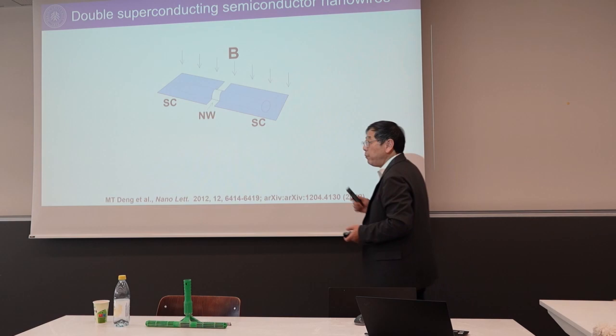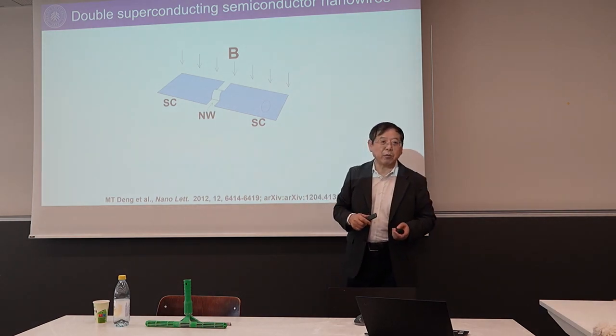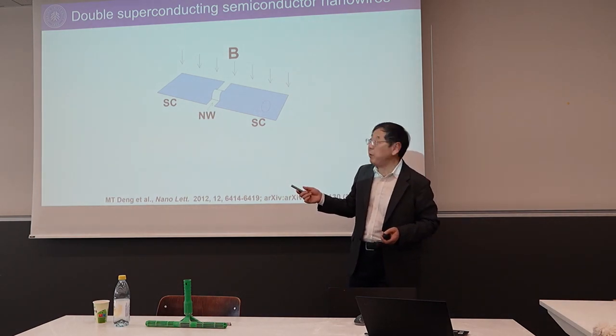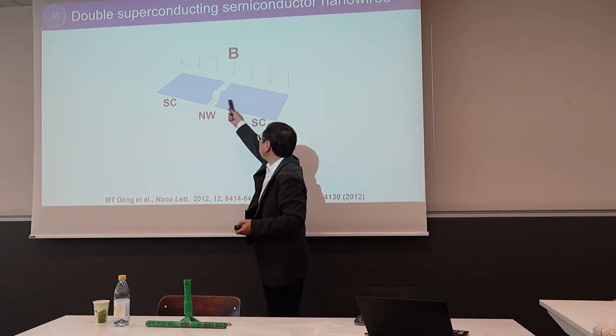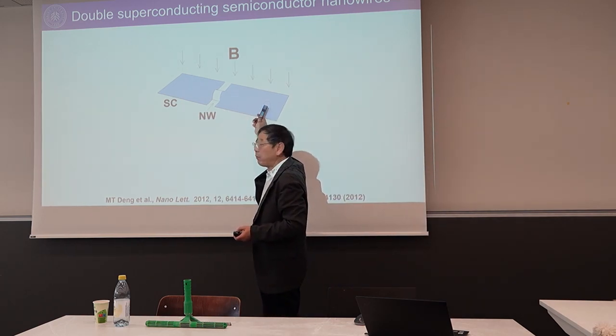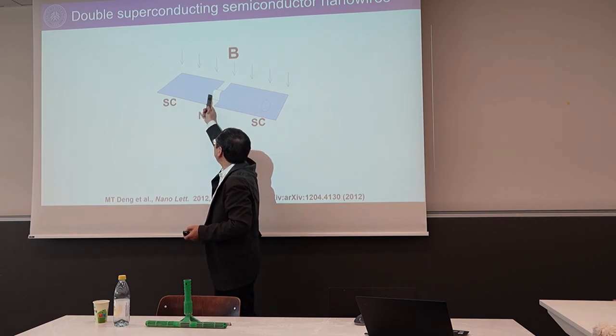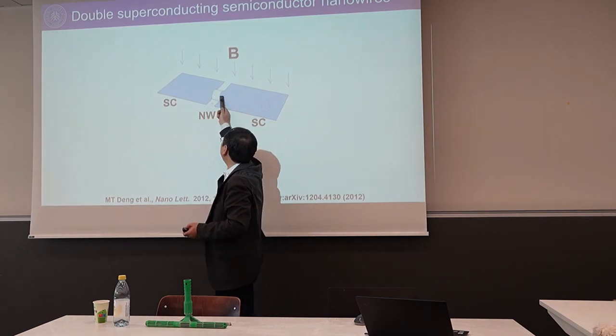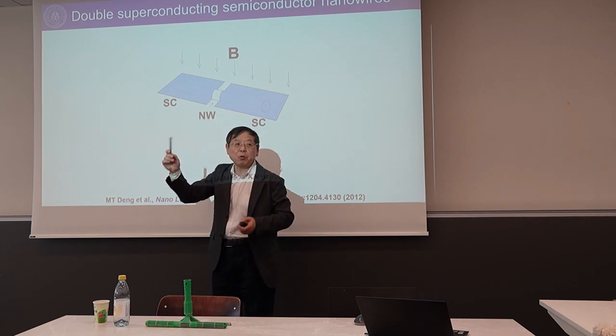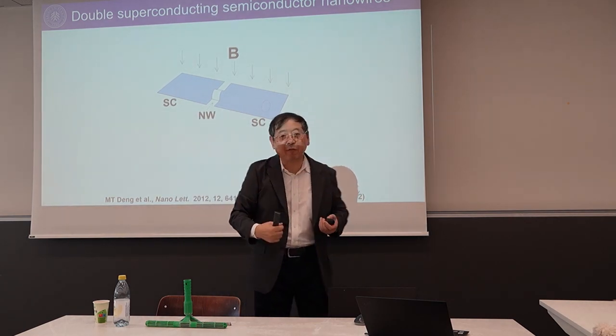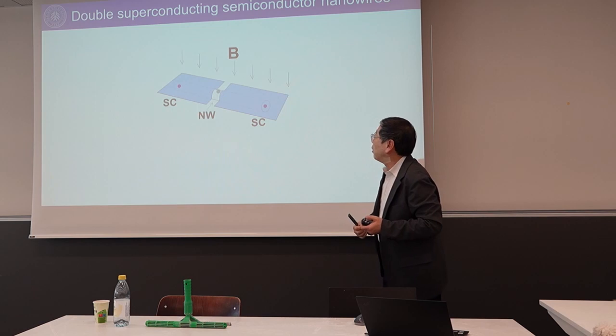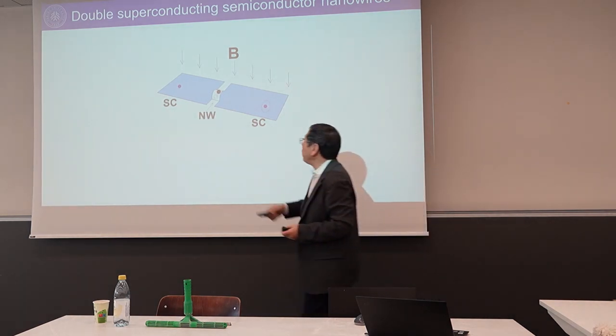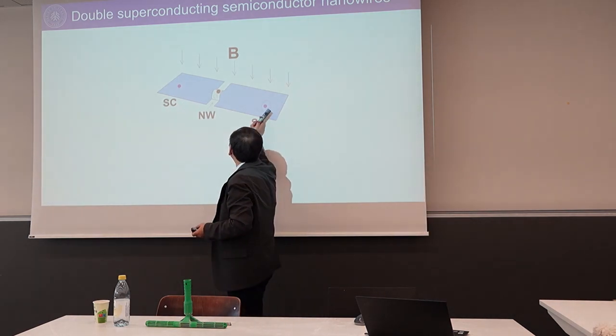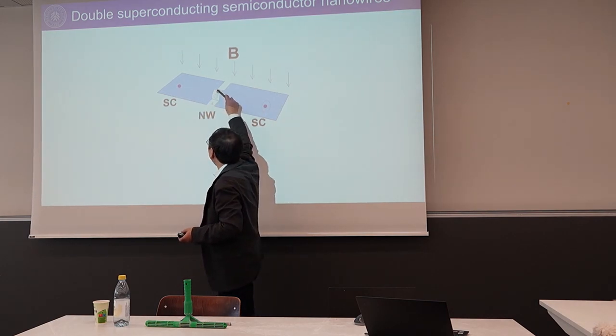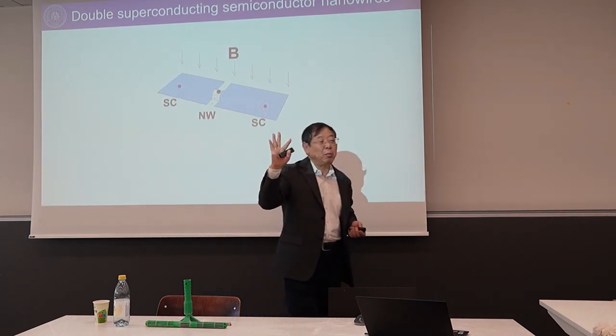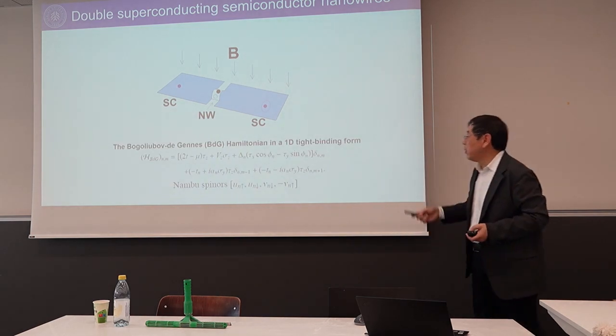We can also simulate this with a model. So we create this piece of topological nanowire. In this piece of topological nanowire, we should have one pair of Majoranas here and one pair of Majoranas here, and these two can interact. Interaction will fuse them and create a so-called particle, antiparticle state. So in this system we should still see the pairs of Majoranas and also the particle state and antiparticle state, and a triple peak structure. We can simulate that.